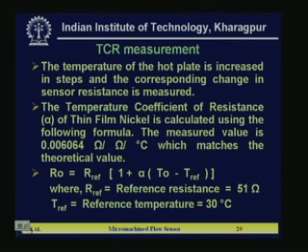So, that is why some error will come into the picture, and at the same time another deviation is due to the fact that you are measuring the TCR of the nickel film and you are not expecting that the TCR of the nickel film will be the same as that of the bulk. The reported result in the literature is the bulk nickel TCR value, that is 0.0064 or 65 something like that, but here we are getting very close to that, and the deviation is because of that.